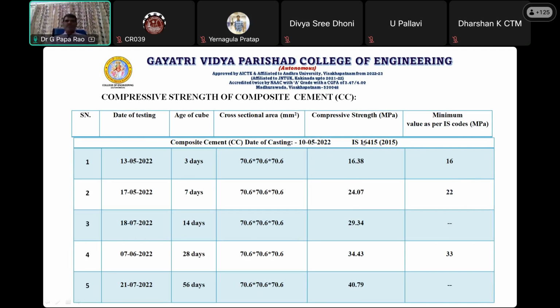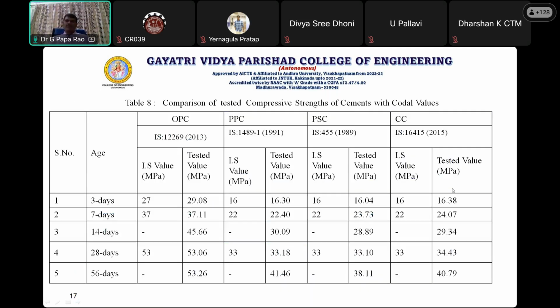Again, composite cement. This is the ternary cement, a mixture of OPC plus PPC and PSC, or fly ash plus slag plus clinker. It got 16 MPa at 3 days, 24.07 MPa at 7 days, and 34.4 at 28 days. Our OPC also, whatever cements we have procured from mass cements, we can proceed further with these cements. First, we have confirmed our cement strengths before going for further investigation.